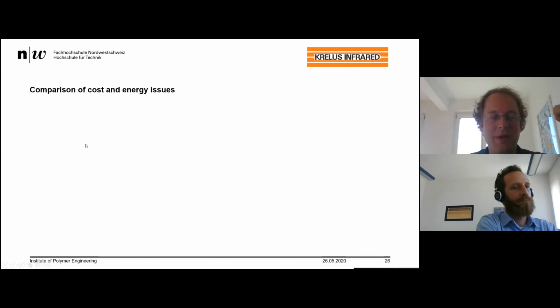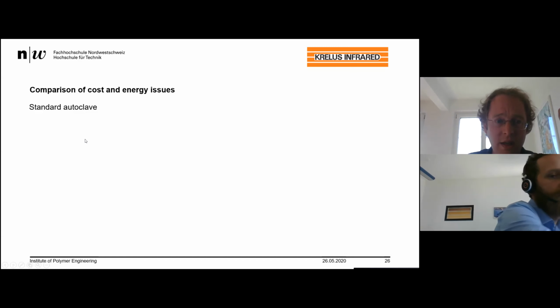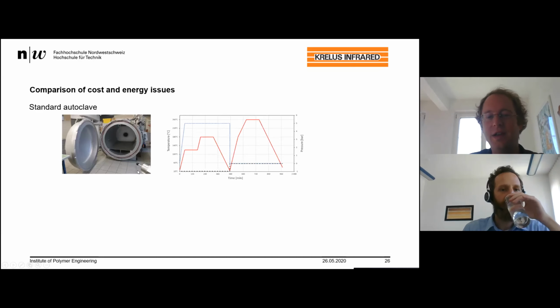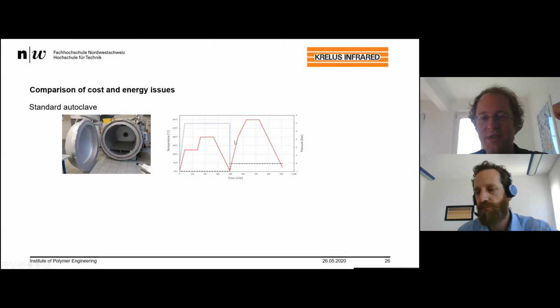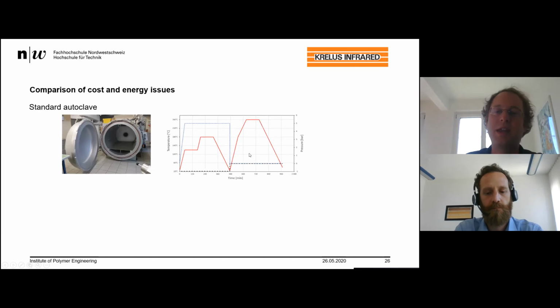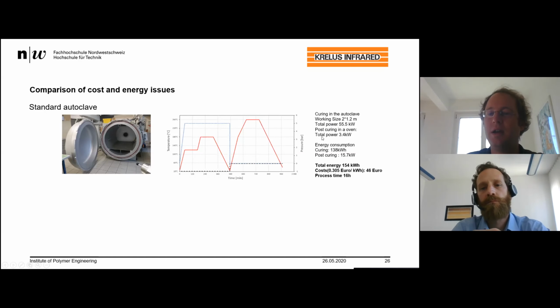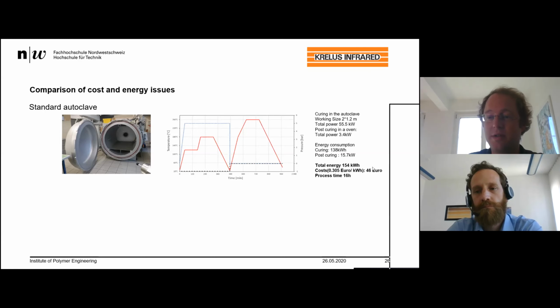Now I want to make a short review about cost and energy issues. If we look at a small size autoclave, and apply again the process conditions for the cyanate ester based prepreg, I know it's a really special material because we have to go to these high temperatures, we can derive some conclusions. In this case, we have this autoclave, with its total power. Again, we have to apply curing for about 8 hours, and then do a post-curing in a convection oven. If we summarize this, we need a total energy of 154 kilowatt hours. This means energy costs are around 46 euros and a process time of 16 hours.